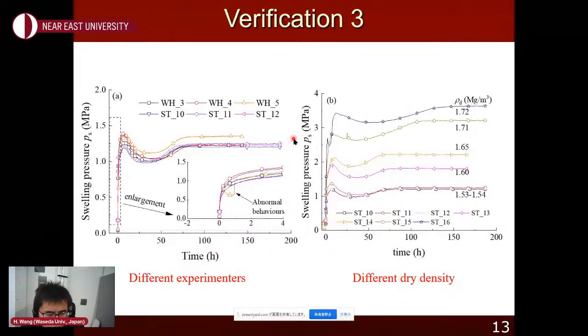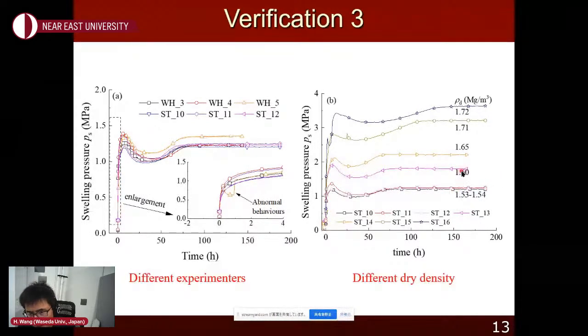In order to see any difference based on the experimenters, we conducted 3 tests by one experimenter and another 3 tests by another one. As you can see, for the same dry density, the measured curve is very similar, although there's some difference, but basically they're quite similar. And for different dry density, you can see the measurement is also quite good. As the dry density increases, the pressure increases.